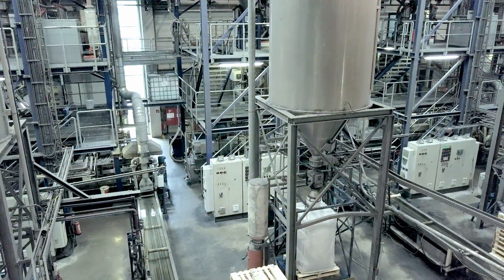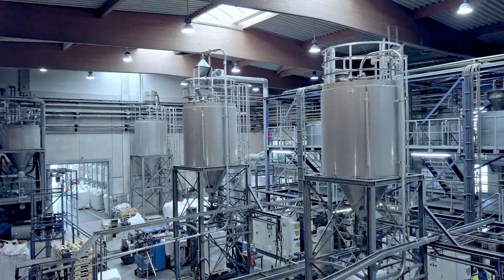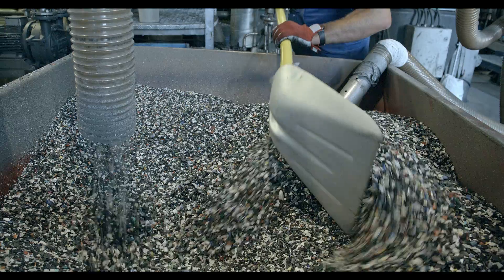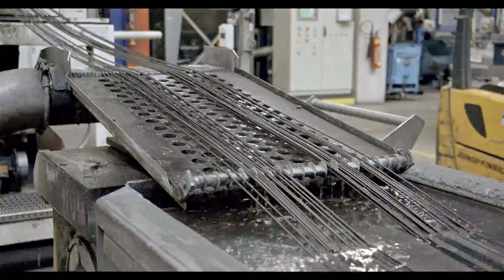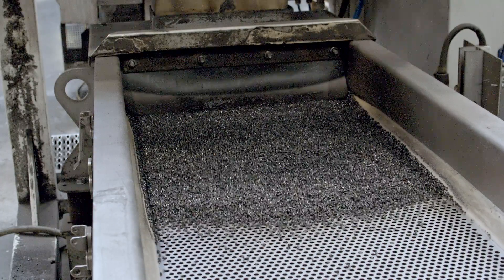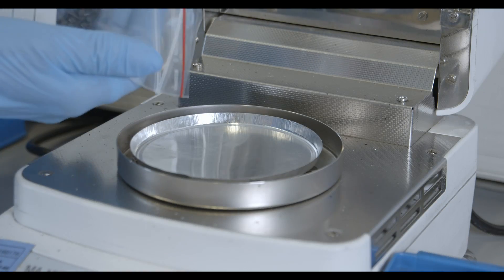The separated metals can of course be recovered. The organic parts, such as wood, rubber, and fluff, serve as feed for thermal recovery. The resulting plastic fraction is size-reduced before it enters the following complex separation processes. At the end of the recycling process, the target plastics PP, PS, ABS, and PC-ABS are separated from each other by type. The separated non-target plastics, as well as the plastics with flame retardants or other substances of concern, are thermally recovered in suitable incineration plants. The target plastics undergo a final quality control before they enter large blending silos, before being extruded or compounded. The end product is a pure, post-consumer recycled plastic in the form of granules or pellets, tested for all relevant rheological, physical, and chemical properties before being delivered to customers.